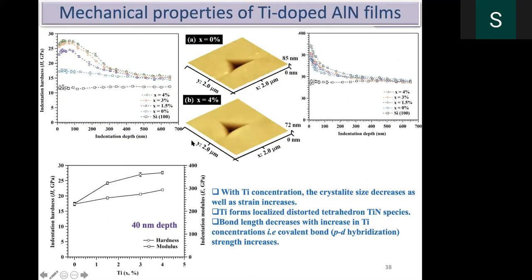Hardness is my specialization in our group, so we always test that. Usually you do indentation at one particular depth, but we did a continuous multi-cycle indentation with different depths in one single indentation. In that process, you can get continuous stiffness measurement also. I did this for all these 4 different kinds of materials and compared with pure silicon. This is the silicon hardness.